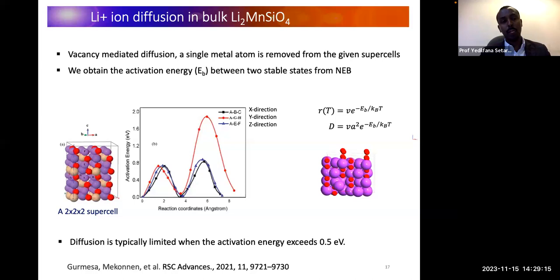But the one that we implemented here is the vacancy-mediated diffusion. We create a vacancy just by removing a single metal atom, and now using NEB, we follow the vacancy. The lithium ion follows the vacancy. So if you calculate the NEB for the vacancy, indirectly you are measuring the NEB for the lithium ion, right? So this is the case study, where we calculate lithium ion diffusion in bulk lithium manganese silicate. This is one class of cathode material with good voltage and capacity. This is a pristine one. We don't add anything, just a pristine bulk material. We only create a vacancy and study the elastic band paths.